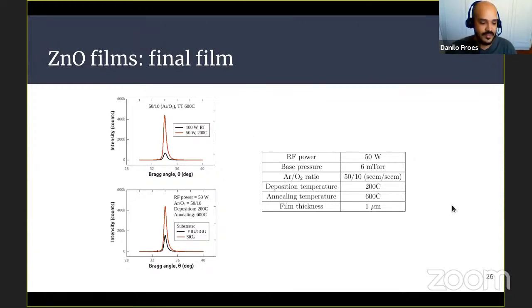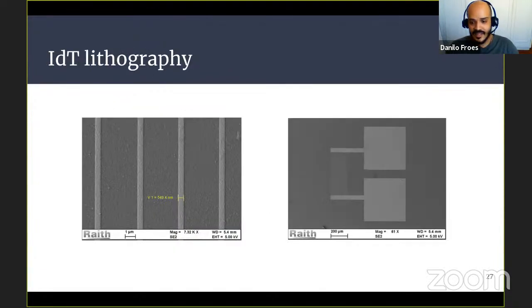I'm going fast here because I don't have much time, but I believe you will have some questions on this. For the interdigital transducer lithography, I had to adapt the process to reduce charging effects. It was very hard to do. Our final interdigital transducers were like this. They were 550 nanometers wide with a periodicity of 4 micrometers. This was the final IDT we obtained.